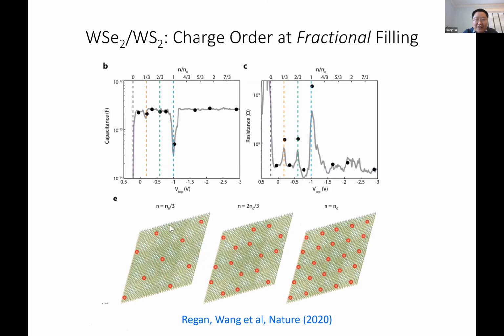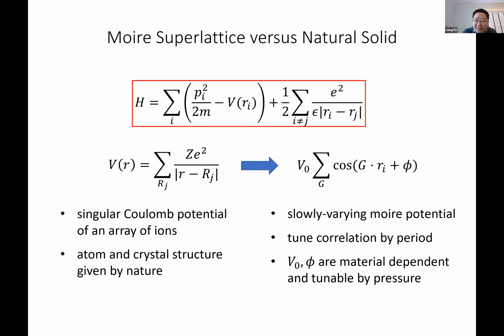For example, at 1/3 filling, you have the charge forming a triangular superlattice, and at 2/3 filling, you can think of it as the missing holes forming a superlattice, right? You can think of it as density waves, or as Wigner crystals being pinned by the underlying Moiré lattice. So this already tells us that the physics of these TMD heterobilayers is very rich and quite different from twisted bilayer graphene. In twisted bilayer graphene, at least so far, all the insulating states are only seen at integer filling. Okay, so this provides a motivation for us to look into the physics of these materials.